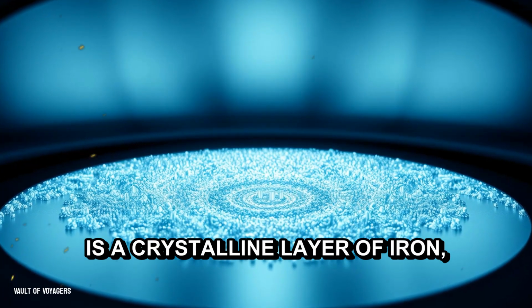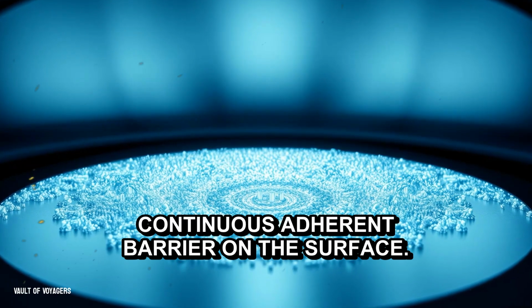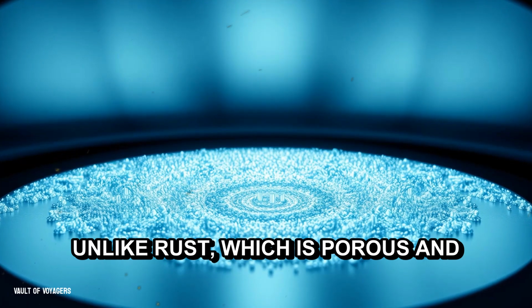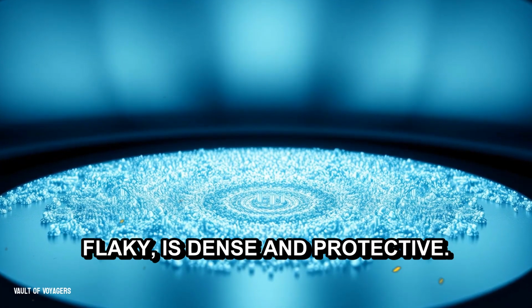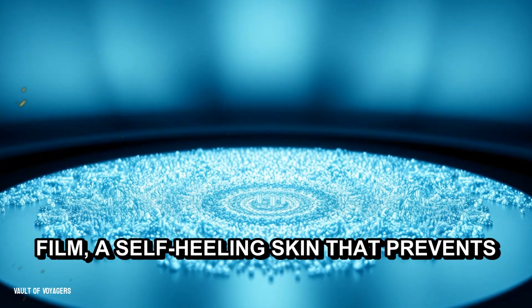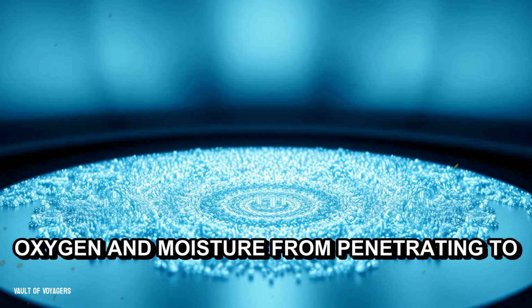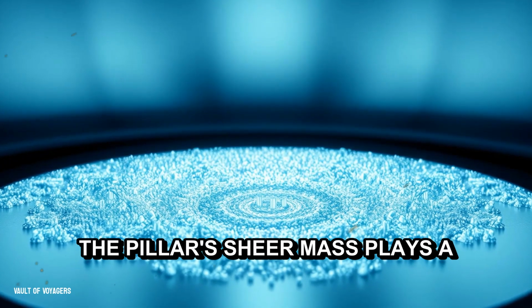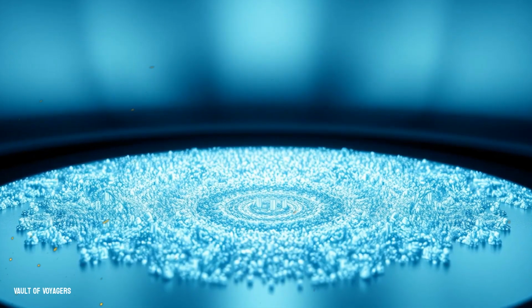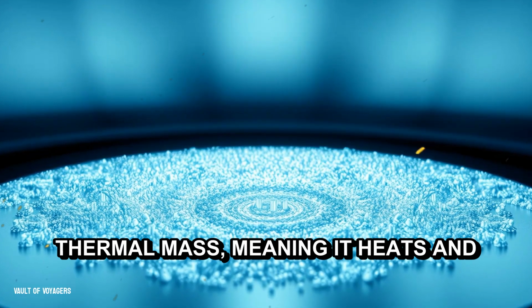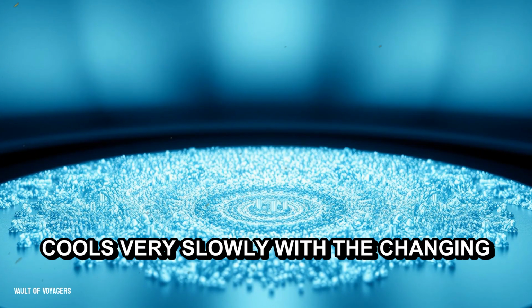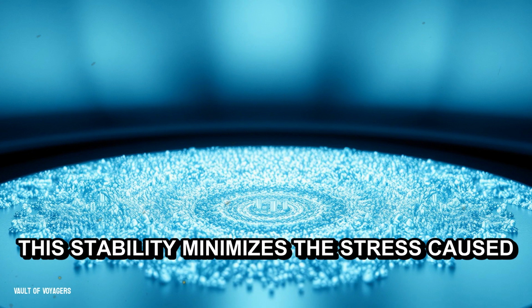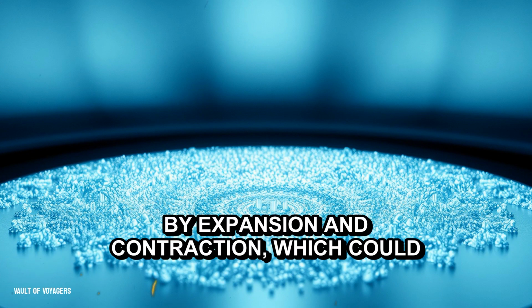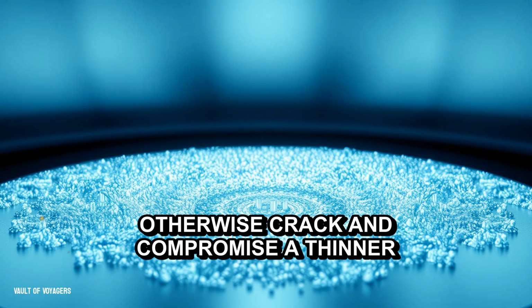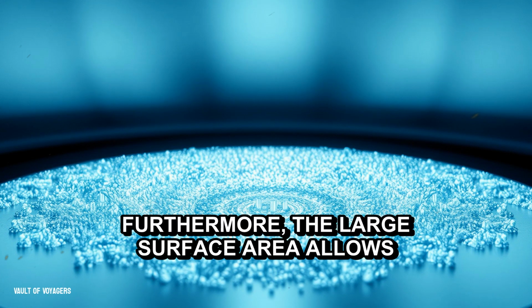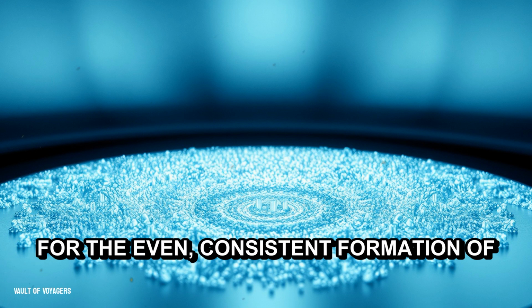It is a crystalline layer of iron, oxygen, and hydrogen that forms a continuous, adherent barrier on the surface. Unlike rust, which is porous and flaky, it is dense and protective. It acts as a permanent passive film, a self-healing skin that prevents oxygen and moisture from penetrating to the pure iron beneath. The pillar's sheer mass plays a crucial supporting role in this process. Its enormous volume provides a tremendous thermal mass, meaning it heats and cools very slowly with the changing day. This stability minimizes the stress caused by expansion and contraction, which could otherwise crack and compromise a thinner protective layer. Furthermore, the large surface area allows for the even, consistent formation of the film.